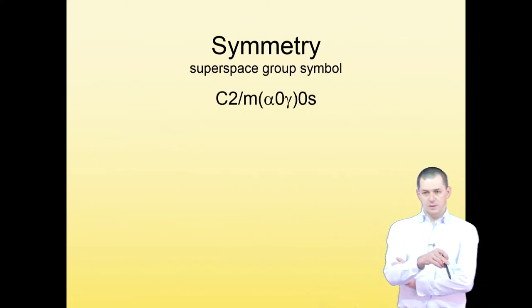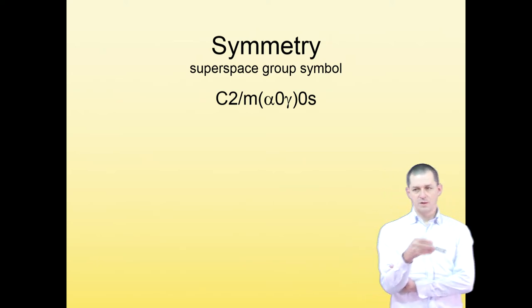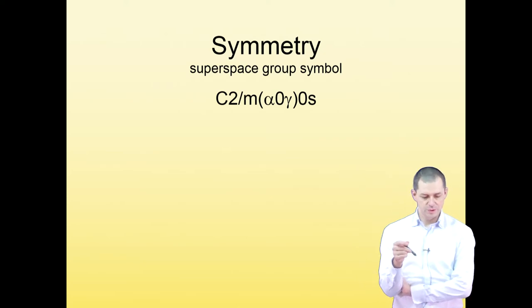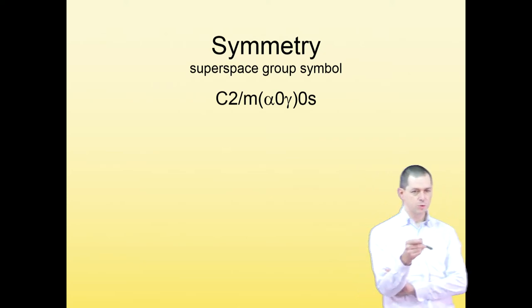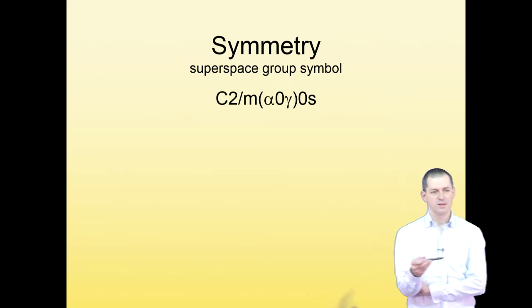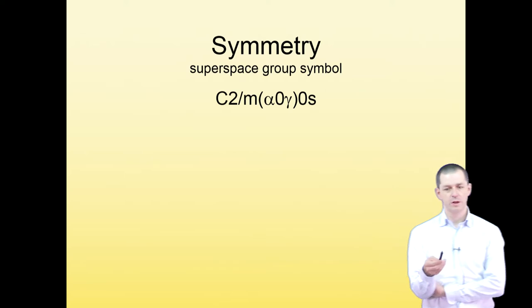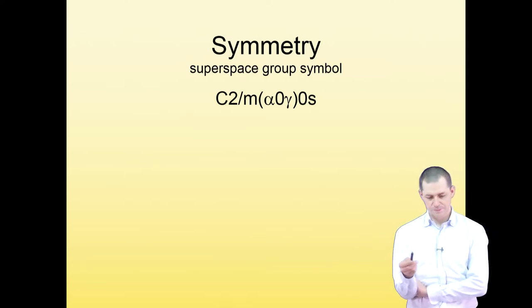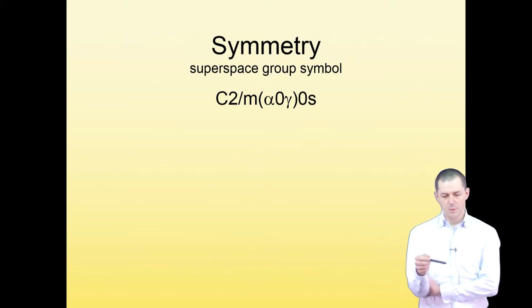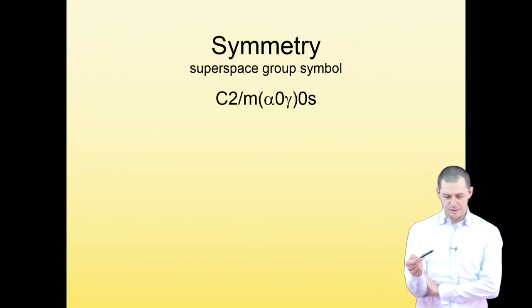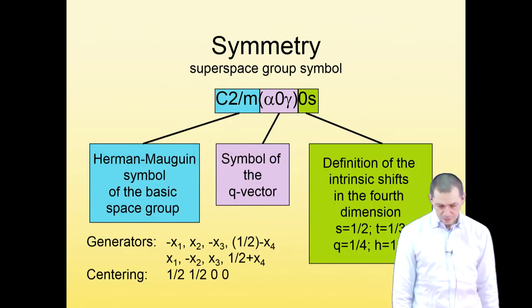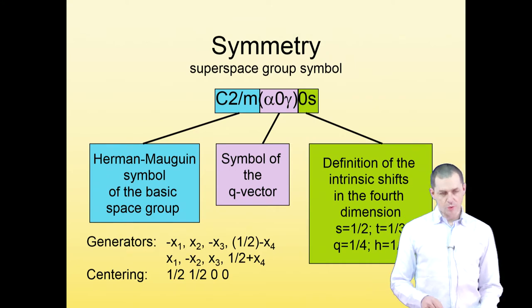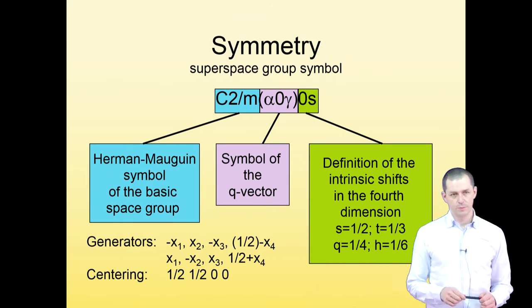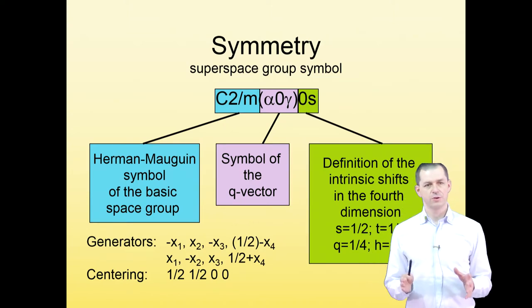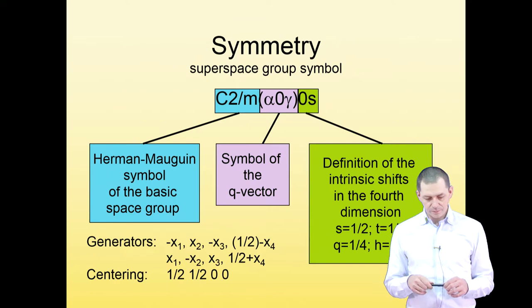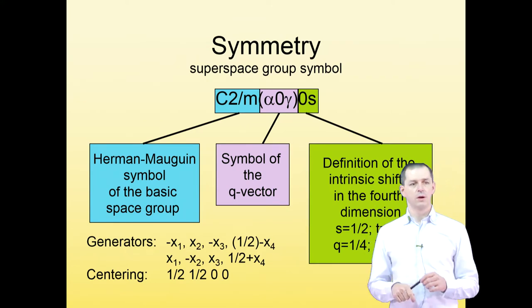I will not go into details of superspace symmetry. That can be quite complicated, but I want to explain briefly the meaning of the superspace group symbol, because this is something you can find if you read literature that contains descriptions of modulated structures. So the superspace group symbol, the one that's most widely used nowadays, is composed of three parts. The first part is just the normal Hermann-Mauguin symbol of the basic space group, so the space group of the average structure that you obtain if you remove all the modulations.